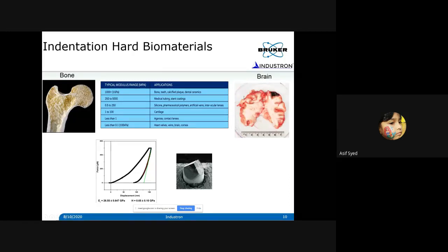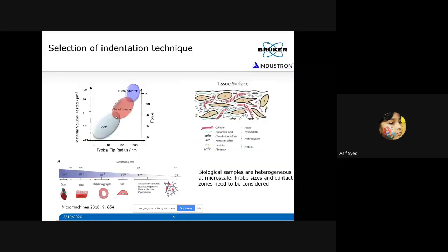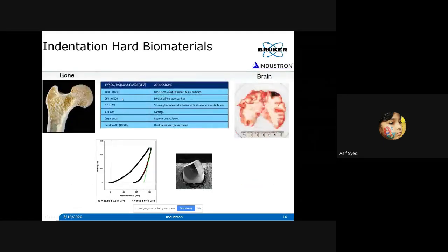Okay. Normally, the way I am classifying hard and soft is based on the elastic modulus. For example, when you have modulus about 1 GPa, it's typical for the modulus of bone. And then if you go down, when you have cartilage type material, it's about 100 MPa, and below that is in kilopascals, 0.1 MPa. Basically, contact lenses or brain or the cornea or veins and heart valves are around 100 kilopascals. So those materials I call soft. I call materials up to about 100 MPa hard, and below that I call it soft. Okay.